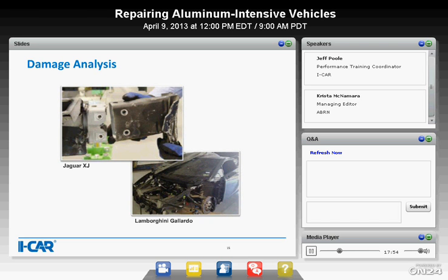So when it comes to damage analysis, when developing a repair plan, in addition to the typical visual damage indicators that we're looking for on your vehicles, we want to pay particular attention to the joining areas. Adhesive and rivet bonded joints may not give the appearance of damage, but extremely close visual inspection is necessary to ensure that damaged bond line does not get missed. When a vehicle is in a collision and that structure is taking that energy, there's a lot of shock that goes through that structure. And again, it's going through each one of those joints in there.